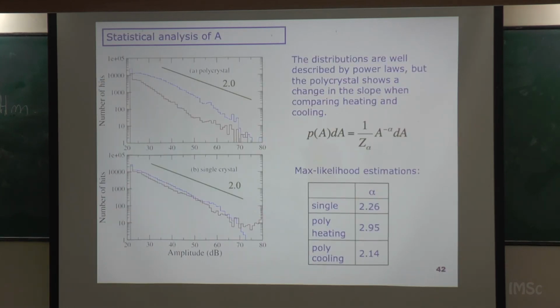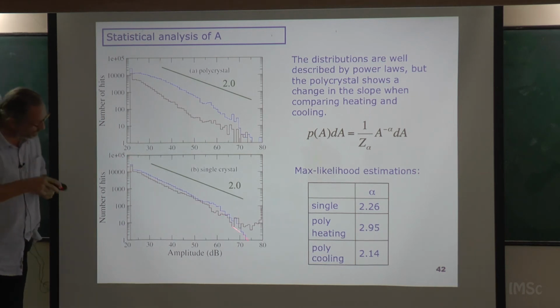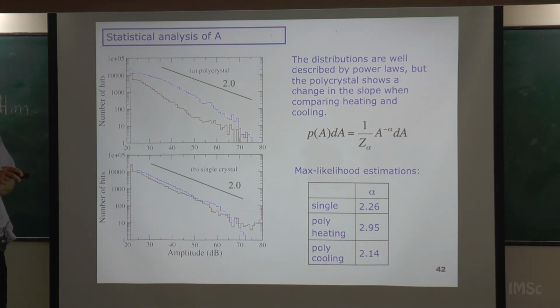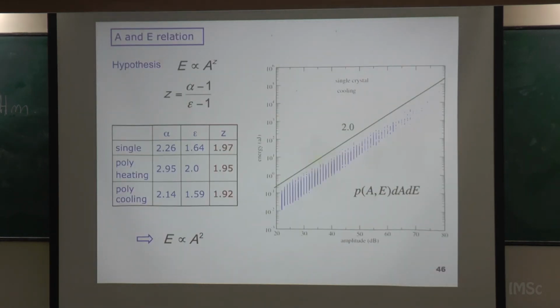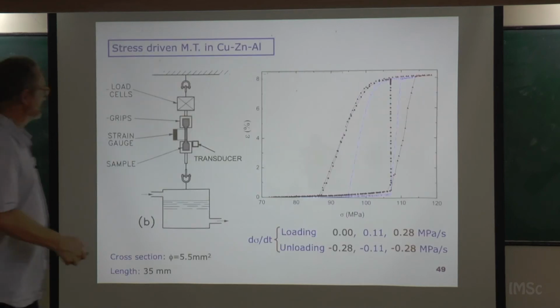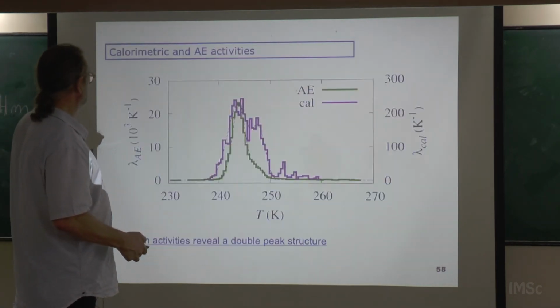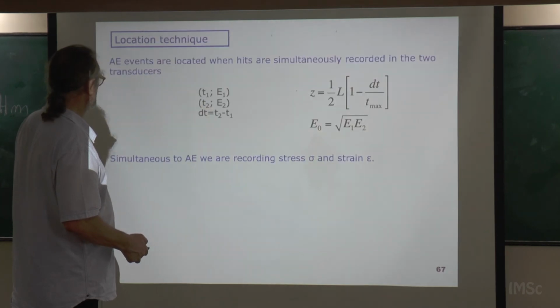Now let me go here. So this is the study of the distribution of, in this case, the amplitude distribution. You plot the histogram of the distributions. For the polycrystal, there are some problems because polycrystals have some extra things in the crystal grains, etc. But for the single crystal, you get something very nice. You get this exponent here, 2.26. You can do the same analysis for many other alloys, and now I go to the very last slide. I can show you more things, but maybe this is the important message that they want to transmit.